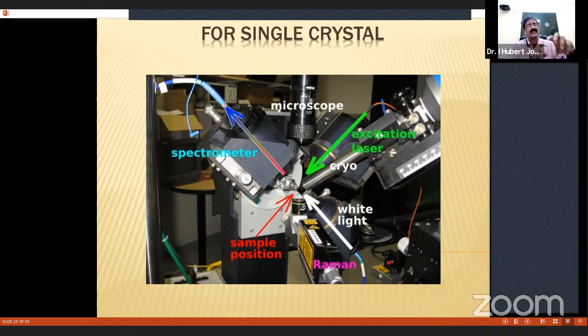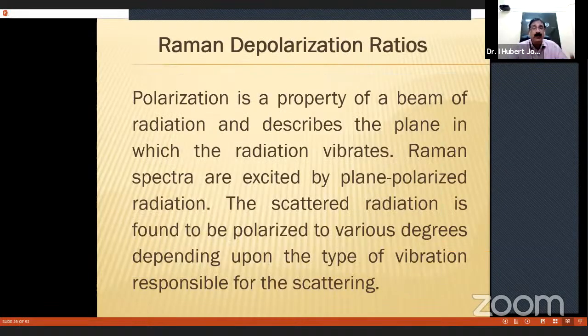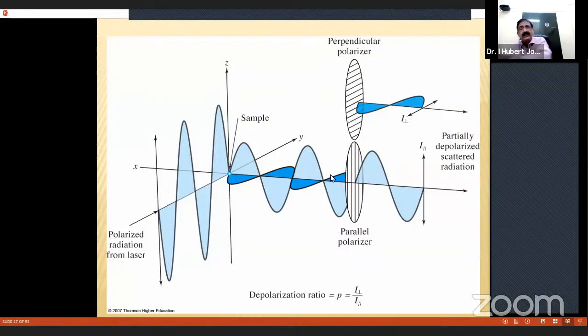In that way, you can change the direction of incident and scattered radiation so that you are able to get information from the single crystal, whether the mode is polarized or depolarized. So with a single crystal using the goniometer, you can get good information from the Raman spectra. Regarding the scattered radiation, if you place the polarizer and analyzer parallel and the intensity is almost the same, then it is depolarized scattered radiation. If placed perpendicular, the intensity will be less. By using the depolarization ratio, we can find out whether the mode is symmetric or asymmetric. So this is used for single crystal spectra.